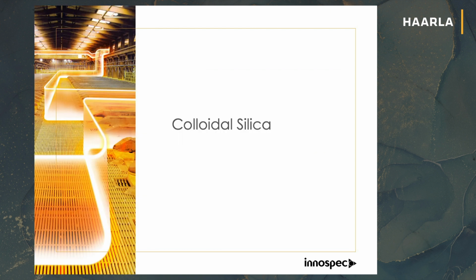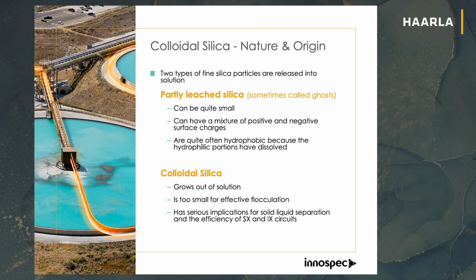The first thing I want to look at is colloidal silica. Colloidal silica is one of these things that you get in all the different ores. Sometimes it's only there at a very low level, which doesn't interfere with the process, and other times it's there at quite a high level, and it can interfere strongly with your purification process. You have two types of silica particles. Ones that are partially leached, so they're quite small, colloidal, and can have both positive and negative charges. The ones that are totally dissolved are not a problem for you. You're looking at the ones that are hydrophobic in nature that don't dissolve, and they can come out.